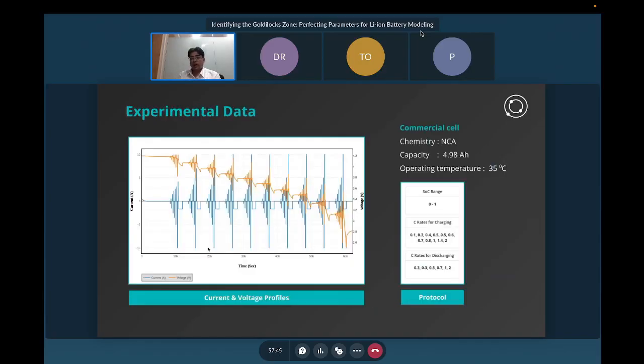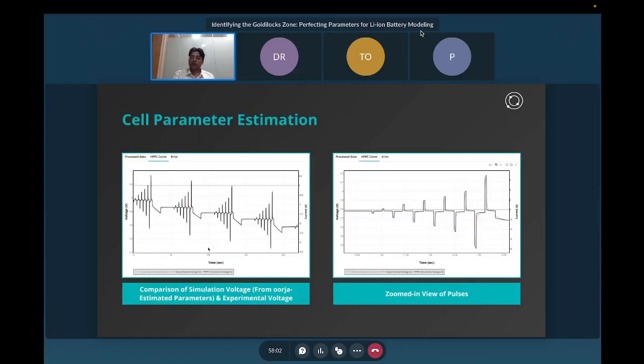Now, after doing this exercise, we actually took commercial cell experimental data and repeated all of these exercises. And here you would see that there are so many charging and discharging pulses for optimization. With this, we could show that apart from the overall HPPC profile, which is exactly matching, overlapping over each other, we could also match the responses over these pulses. This is the zoomed in view of these pulses, and we could match the responses from our simulations by doing the parameter estimations with the actual experimental response.